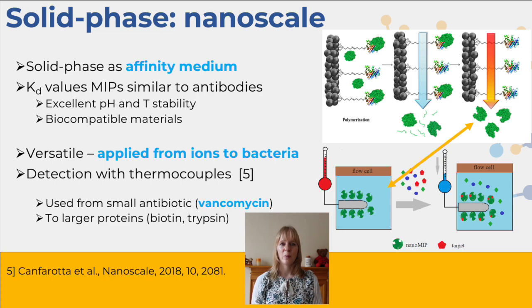In order to make it very simple, we had some of these polymer materials in a liquid and we functionalized it onto a thermocouple, which is something that measures the temperature. Even in a nanoparticle format, they still retain that porous structure. So we modified the thermocouple with these materials, and as soon as something bound to it, again your heat flow through your thermocouple was impacted. And we could use that change measured by the thermocouple, and bearing in mind thermocouples are really cheap, to determine how much of your material was present. So we could quantify the amount of vancomycin that was present somewhere. Vancomycin is not necessarily so relevant for environmental applications, but it's very important in a hospital where you want to know exactly what concentration people have.